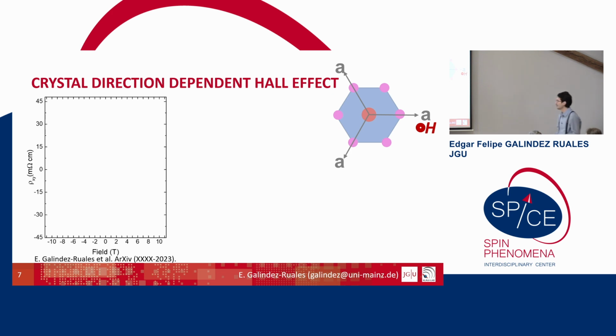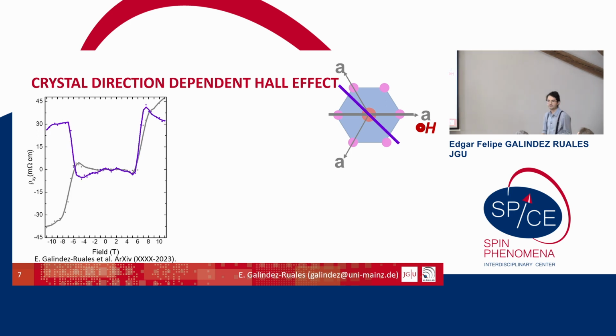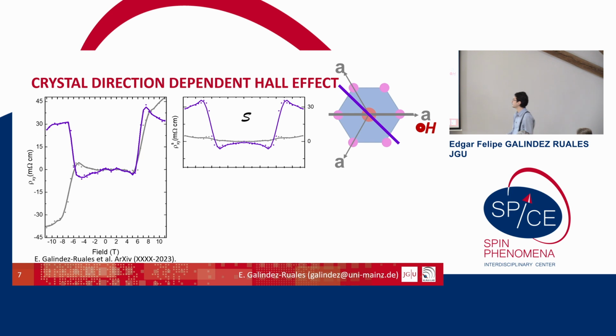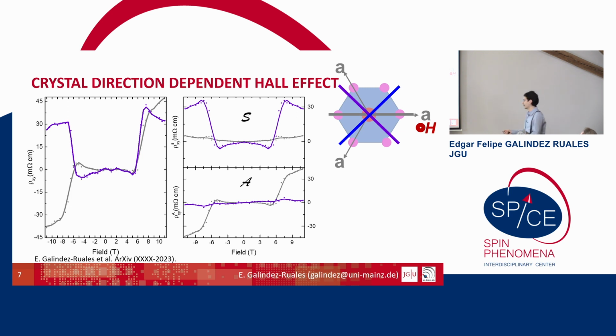And then what happened? When we measure along the a-axis, we have this antisymmetric signal that I showed before, but then we pattern something at 45 degrees, and then we have a totally symmetric signal. That was surprising, because we passed from a fully antisymmetric signal to a fully symmetric signal. And you will ask me how fully symmetric. So we just plot the symmetric part, and you see that the graph at 45 degrees is more symmetric than the one at 0 degrees. And when we plot the antisymmetric part, you have a huge contribution when the whole bar is patterned along the a-axis.